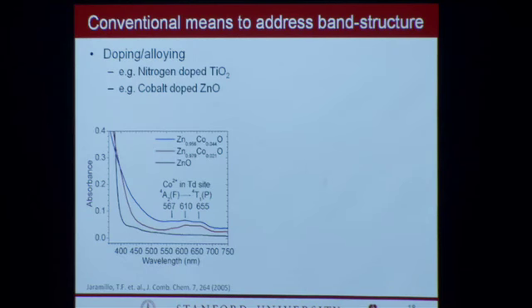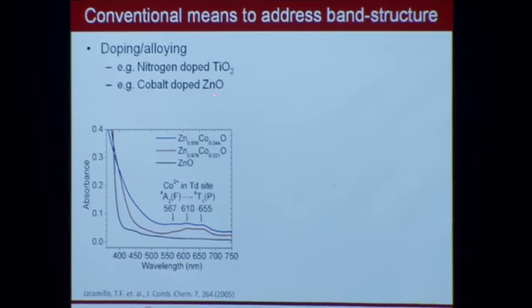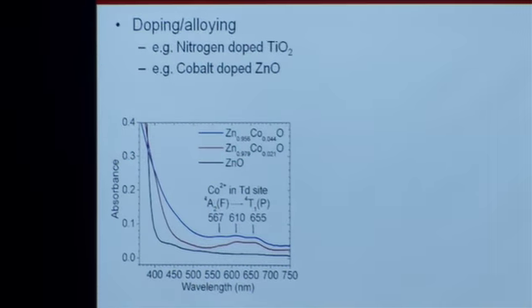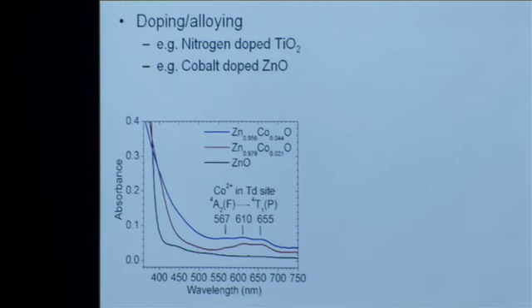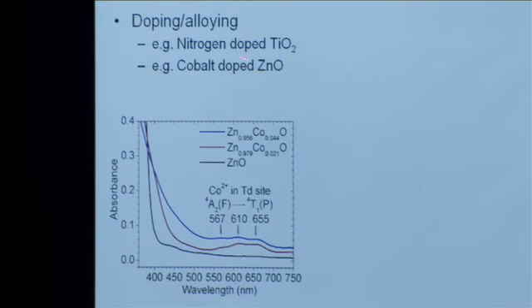So what are common approaches that people have used? I mentioned that this whole field has been predicated on finding that one material that can do it all. So people really take something that works reasonably well in some sense and then try to improve it. Examples are, for instance, titanium dioxide, which works beautifully with UV light. Zinc oxide works beautifully with UV light. And the question is, how can you make it absorb more solar photons? Well, people have accomplished this ultimately by a doping and alloying approach, by incorporating, say, nitrogen into that TiO2 lattice, incorporating cobalt into the zinc oxide lattice.